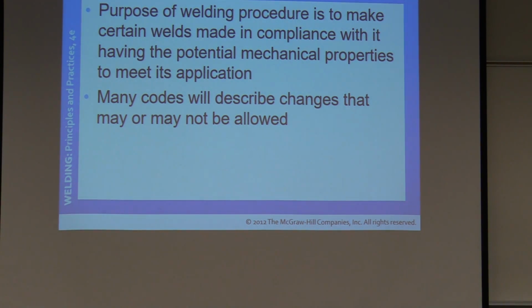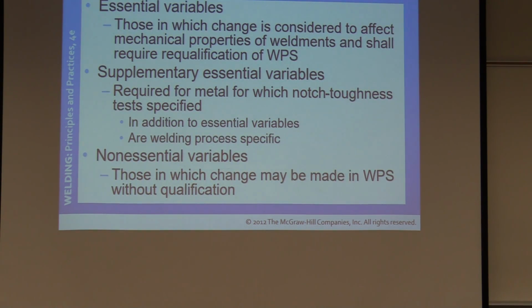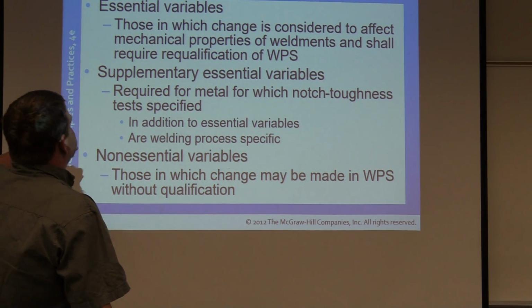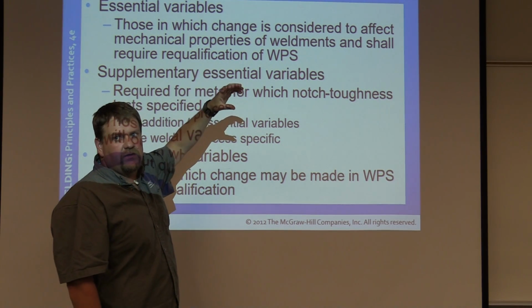Certain changes can be allowed. However, typically most companies and most insurance companies are very hesitant to do that. Right, here's your essential variables versus your supplementary essential variables, non-essential variables. Essential variables are those in which a change is considered to affect the mechanical properties of weldments and shall require requalification of the WPS. Okay, so that means if you change, for example, the material, the pipe that you're welding, from an X52 to an X42 or from an X52 to an X72, it's an automatic essential variable, you have to requalify that procedure. You're not just going to keep welding on it, okay?